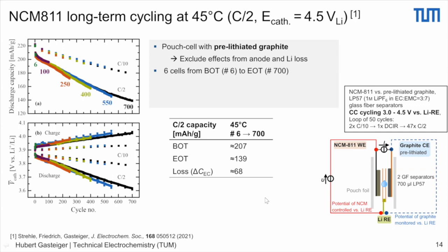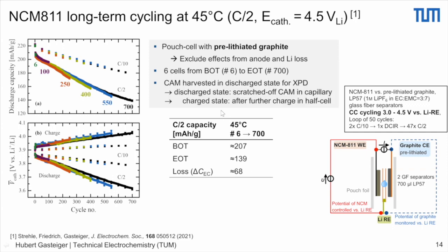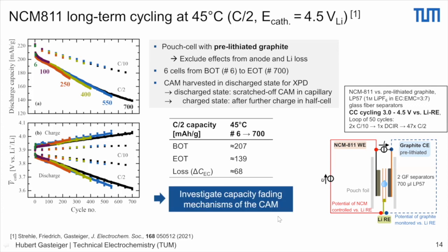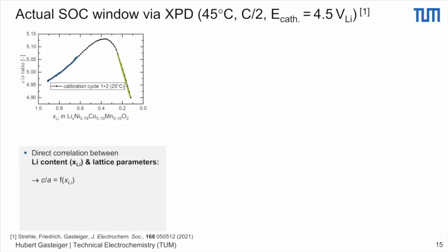capacity retention, roughly. And so then what we did is we harvested the cathode active materials after these different numbers of cycles. And in the discharge states, and measured them in a capillary for X-ray powder diffraction. And then in the charge state, we used these electrodes, charged them in a half cell, and then repeated the experiment in the capillary. And so with this, we want to investigate the fading mechanism. So this is shown in the next slide, where we have a calibration curve for the C over A lattice parameter ratio as a function of the lithium content of the CAM.